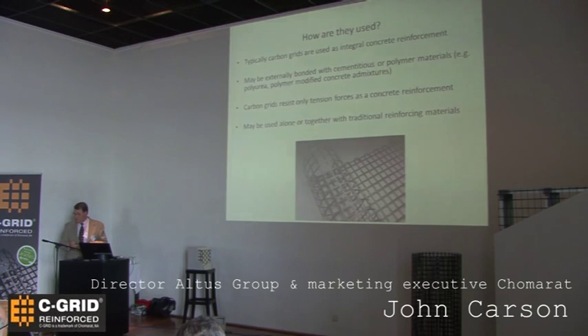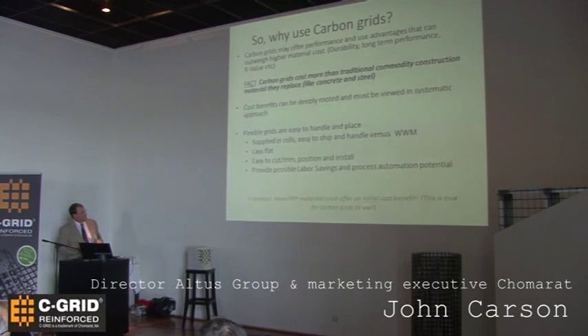In our case, the C-grid reinforcement is generally always used inside a concrete structure, integral. However, it could be used externally if it's mechanically fastened. And you can externally bond the material with cementitious or polymeric materials, like polyurea or polymer modified concrete, some of the high technology materials that are on the market today. They resist tension forces, and they can be used in combination with traditional reinforcing materials like steel reinforcement.